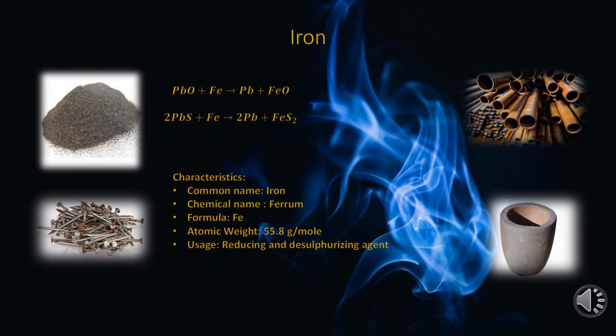Iron is not only a reducing agent, it is a desulfurizing agent. Adding iron to your sulfide ores such as galena, argentite, sphalerite, chalcocite, cinnabar, and a few others, the sulfides will decompose, forming iron sulfide complexes. However, sulfides that contain copper, such as chalcocite, millerite, which is nickel sulfide, and sulfides of cobalt, will only partially be desulfurized. Oxides will be reduced by the iron, such as the lead oxide that is used as a collector